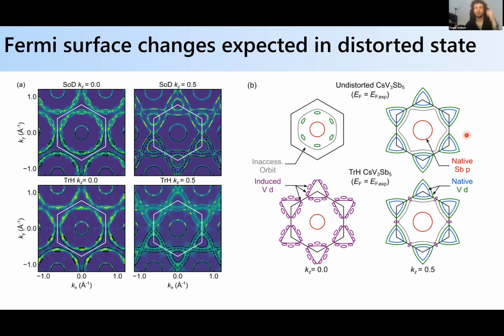Can you say something about the evolution of the anisotropy, let's say of resistivity or maybe other properties too, with respect to the C-axis? This seems to be quite a two-dimensional material. So the question is, how does CDW affect the anisotropies? Also, you mentioned at some point that there could be in-plane anisotropy. I wonder if that's seen anywhere except for STM, this kind of peaks and so on.